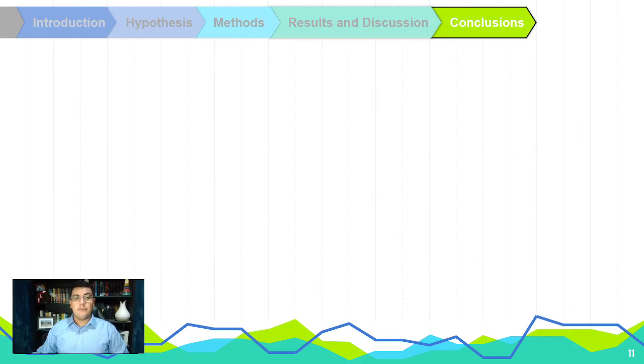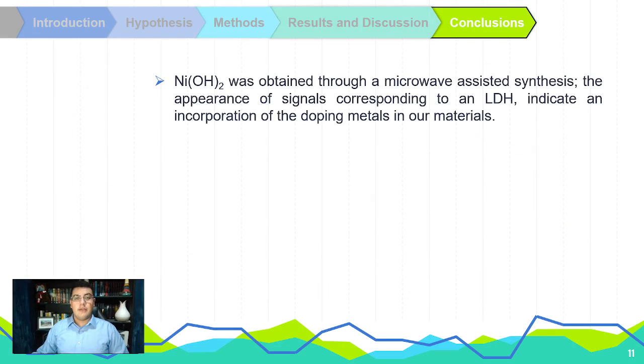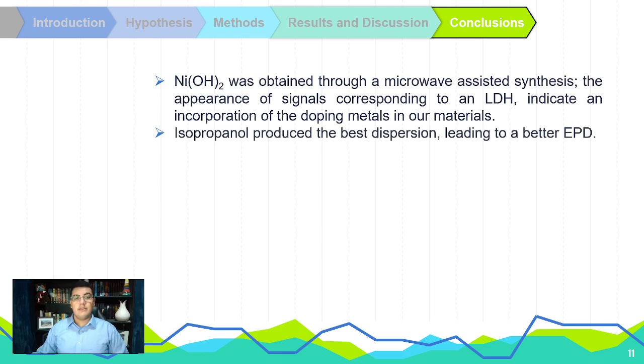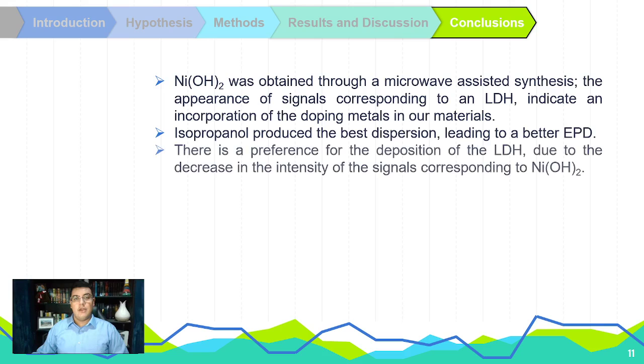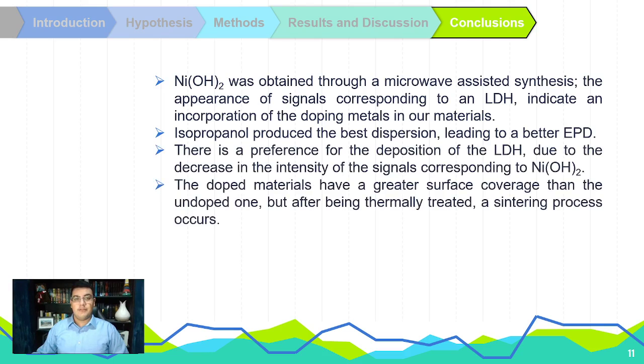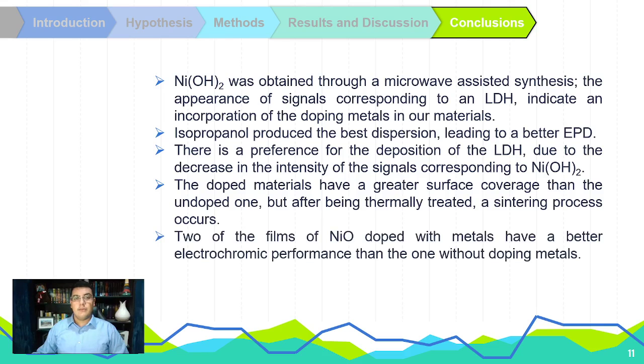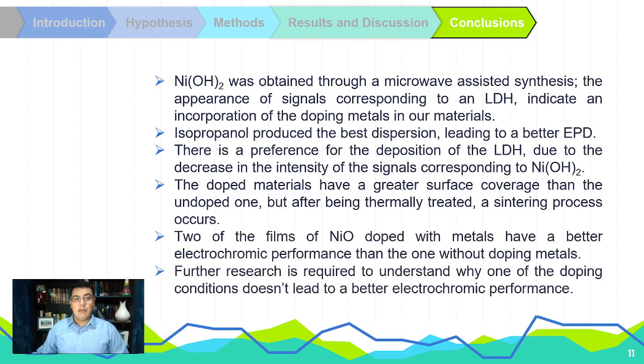As the conclusion obtained from this work, the microwave-assisted synthesis led to the formation of the nickel hydroxide phase with the incorporation of our doping metals in the LDH phase. Isopropanol is the best solvent, producing the best dispersion and leading to a better EPD. We also conclude that the EPD has a preference for the LDH over the nickel hydroxide, and that the thermal treatment leads to a sintering process. Also, two of the metal-doped nickel oxide films have better electrochromic properties than the undoped one. However, further research is required to understand why the other doping condition didn't show this improvement.